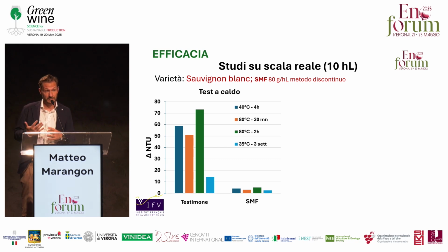This is the heat test. Different heat tests have been compared and contrasted because different companies, different countries use different tests. In blue, 40 degrees, 4 hours. In orange, 80 degrees, 30 minutes. Green, 80 degrees, 2 hours. Light blue, 35 degrees, 3 weeks.